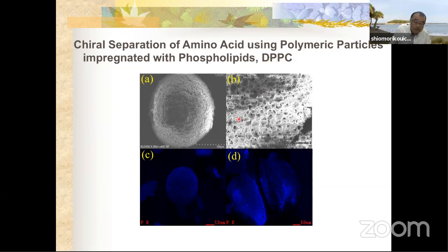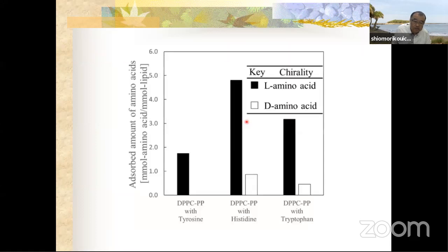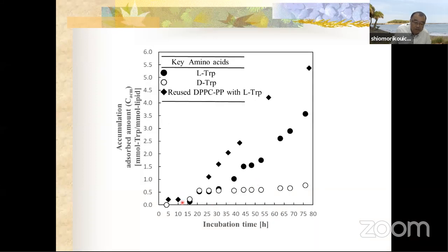DPPC supported on the particle also shows the chiral selectivity like this. DPPC on the polymer particle shows the L-type selectivity like this. D-type amino acid did not adsorb on the particle here. So the time course is shown here. Only L-type amino acid tryptophan was adsorbed on the particle like this.